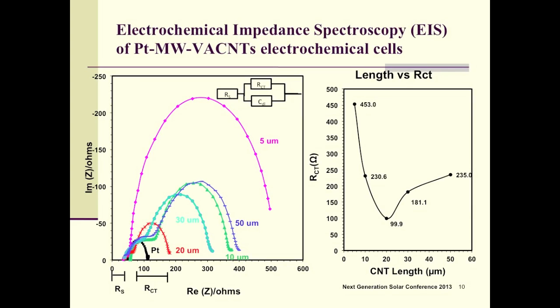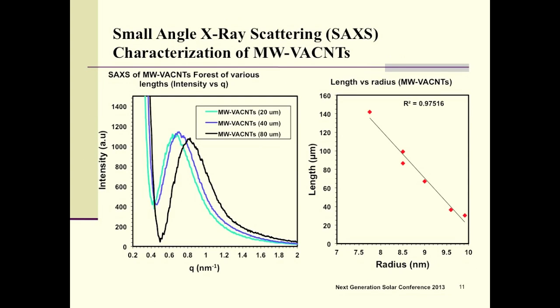And then we also tried to revisit our SEM images, but it was very hard to get any quantitative details from them. So we decided to go for small angle X-ray scattering measurements for these carbon nanotube based electrodes. Here are the plots, and Q is the scattering vector. By using the value of Q at the maximum peak, we can calculate the average radius of our carbon nanotubes. The right plot is carbon nanotube length versus the radius, and we found that with increasing length, the radius of the carbon nanotube is decreasing.